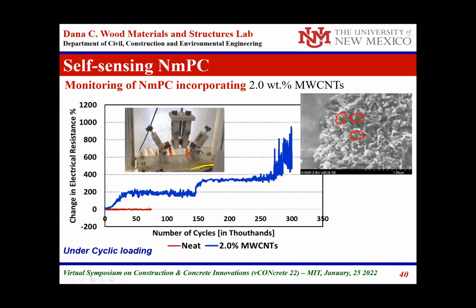This is the neat polymer concrete, the same polymer concrete mix made of epoxy concrete, but without any of the carbon nanofibers. With the high range of change in stress we are doing, the specimens failed after 50,000 cycles.